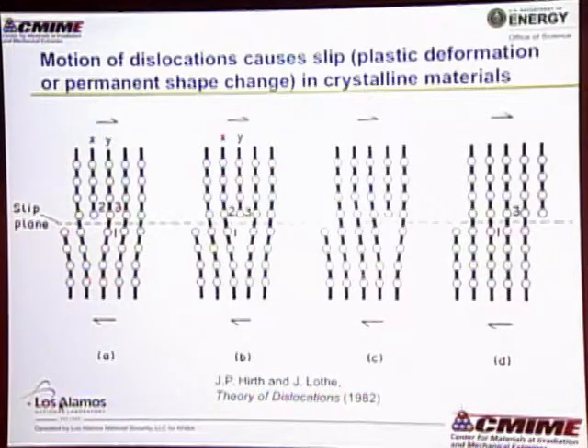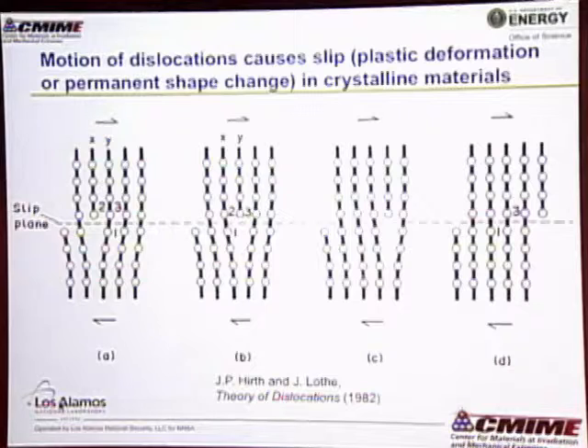So a way of looking at this schematically, if we imagine again our columns of atoms, we've got our extra half plane right here. We've got atom 2, atom 3, and atom 1. What happens here is as you apply a stress to this material, individual bonds break and are remade from one step to the next. So in this case, we broke 1 to 3, we form 1 to 2. You can do that again, and then you can do that again. And what you get at the end is this step at the end of our material. You repeat this billions and billions of times, to use Carl Sagan's terminology, and you'll actually be able to bend your paperclip. This is the basic physics that occurs for bending paper clips. It's what happens in car crashes. You name it, this is what dictates it.